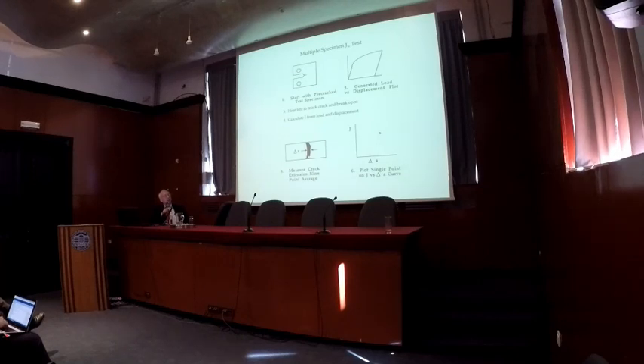And for steels, heating oxidizes it. It works very well. For some non-ferrous materials, you might need other techniques. But for steels, heating marks that crack tip. And then from this you get the crack extension, from the curve, you can get the J using the formulas I showed you before, and you get 1 point.